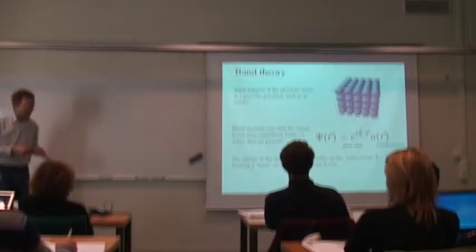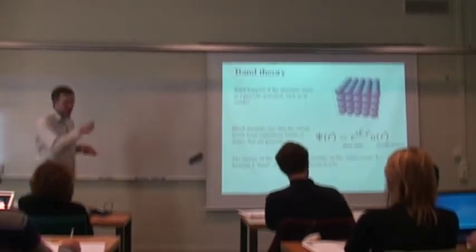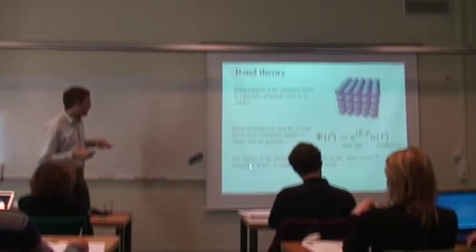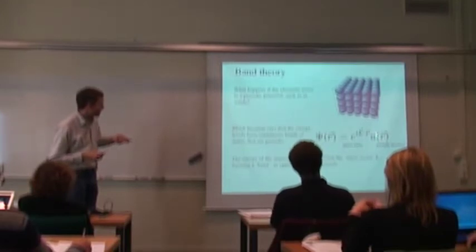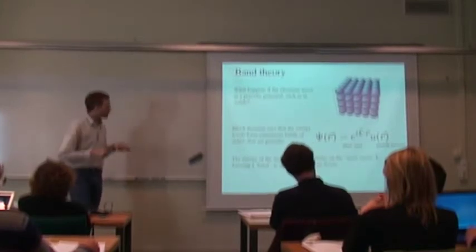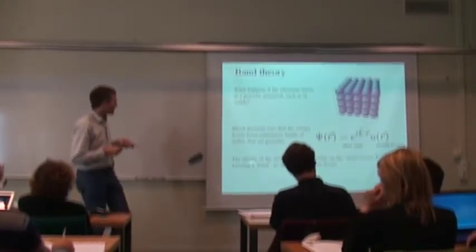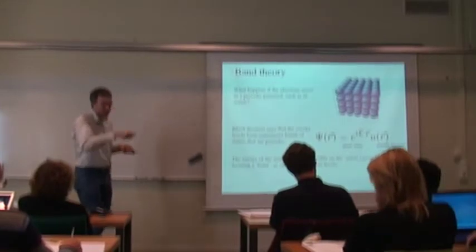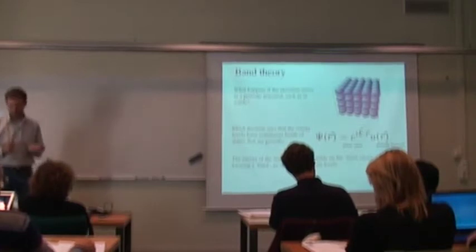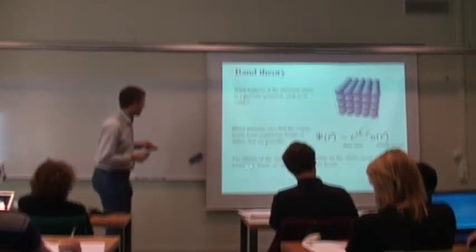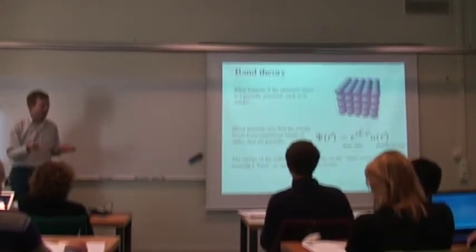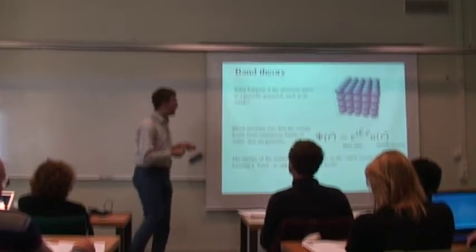The only thing you have to remember here is that the energy doesn't form discrete levels, as in, say, hydrogen atoms, but actually depends smoothly on this parameter k here. So the energy depends smoothly on momentum, and that's why they do not form single isolated energies, they form bands of energies. And we're going to use these bands to explain the difference between insulators